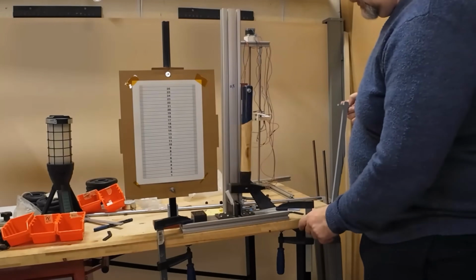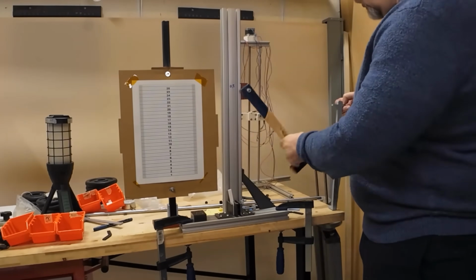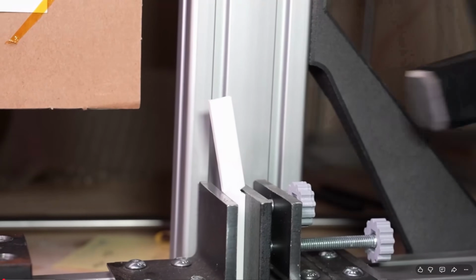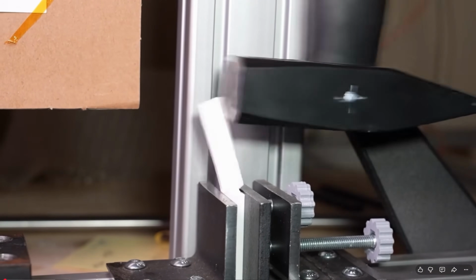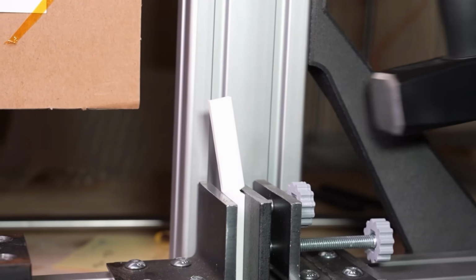A few overall specifications about PC-ABS. It is quite a strong industrial filament, and it tries to combine the advantages of these two base materials. I tested several brands, and I can see that the biggest advantage of this filament is impact resistance. Earlier I had my DIY tester which I use, and almost every time when I tried to test PC-ABS, there was no break under my half kilogram hammer. So the impact resistance is very high with these materials.